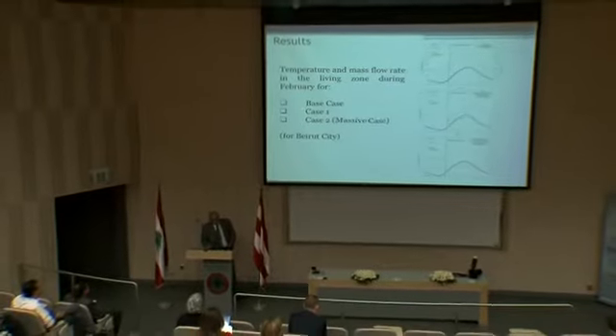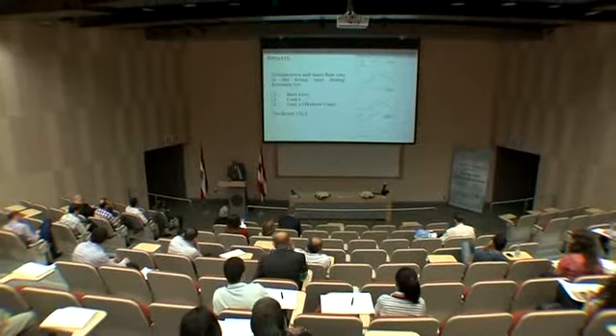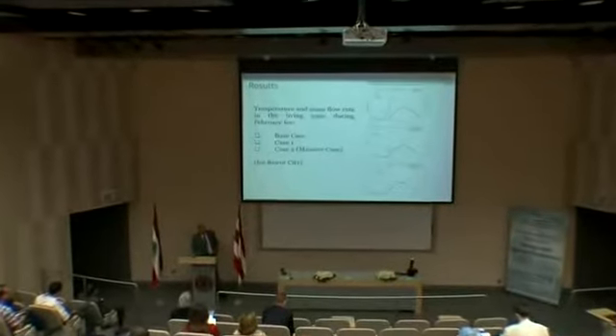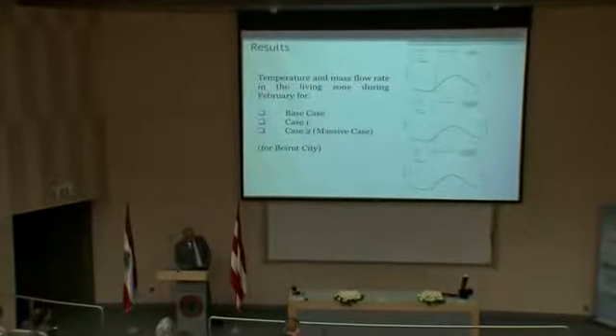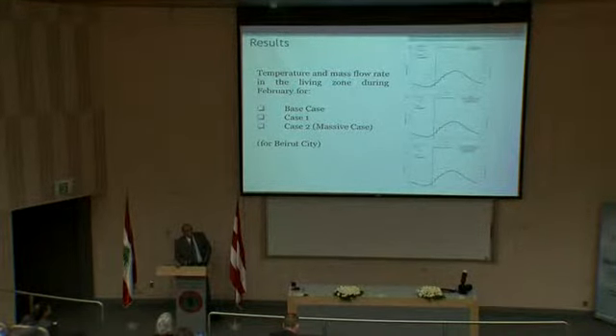Now, we ran the simulation for the base case, case 1 and case 2, talking now about the living zone. During the months of February, when the temperature is low, the controller was set at its minimum value, because the temperature outside is cold. So the controller did not try to bring in the outside air. It only brought in the outside air that is enough for air quality.